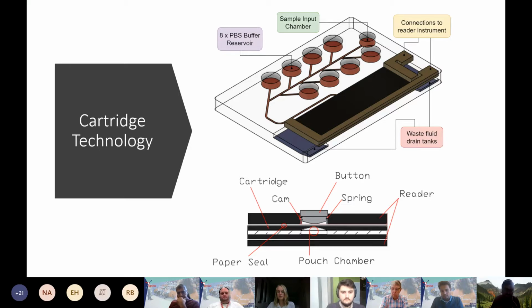We've identified the use of urea as a suitable washing buffer for the recycling step because it's non-toxic and its properties allow us to not harm the aptamer binding to the electrode layer. So it doesn't affect that aminopropylsilane binding that we're using. And we've also set it up in a way that it's beneficial from the business aspect for translation, which allows it to be used commercially outside of a lab.